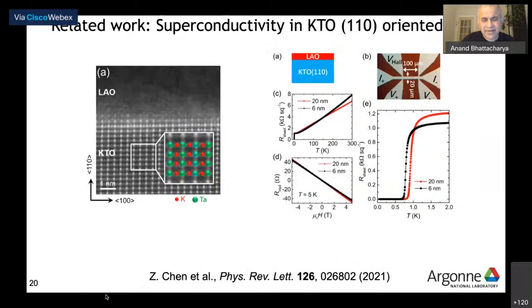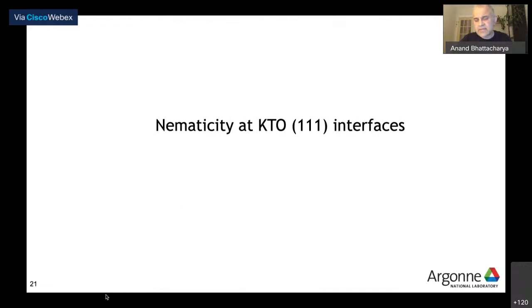All right. This is the slide I was looking for earlier: following our work, very soon actually, because KTO was well studied, other groups had samples that had 2DEGs on other surfaces. For example, this group in China reported that they found superconductivity also in the 110 surface, the 110 interface. So the one that is not superconducting is 001. Both 110 and 111 are superconducting, and the 111 has a TC now as high as 2.5 Kelvin in our lab.